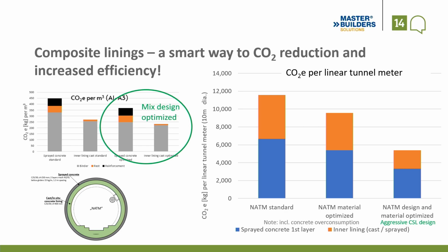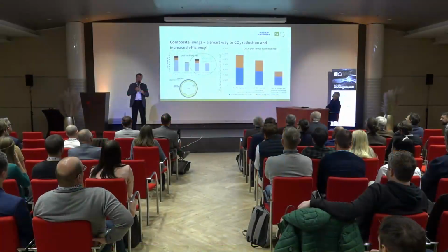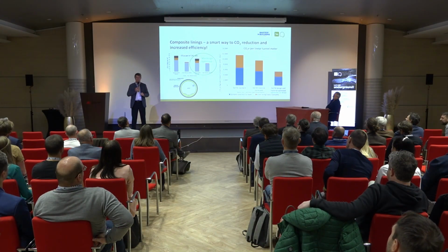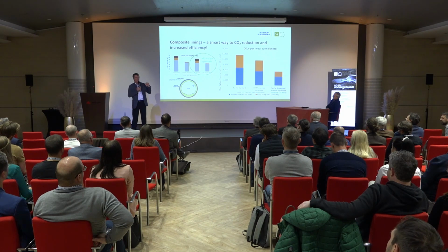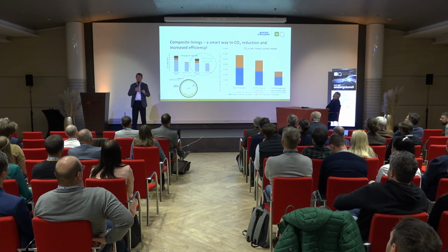And then it's optimized. And then, in addition, you can ask yourself, if we all know that we always overspray the concrete, that we ask for 25 megapascal, but job site measurements show 50, 60 megapascal. Why can't we specify higher? Why can't we incorporate the overspraying to a certain extent? Can't we reconsider the minimum thickness? Why is the minimum thickness everywhere the minimum thickness?